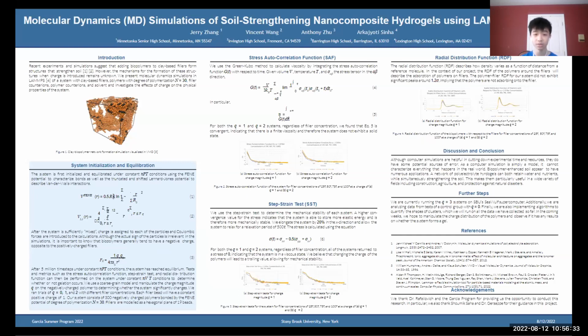All of our systems did not show significant peaks of large magnitudes around the cutoff distance of 1.2 sigma, indicating that polymer filler adsorption did not occur. Our data supports the conclusion that both biopolymer charge magnitudes of Q equals 1 and Q equals 2 do not in fact induce gelation, nor do they lead to significant network formation.